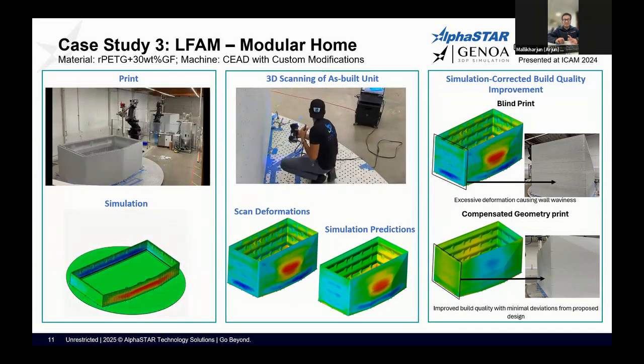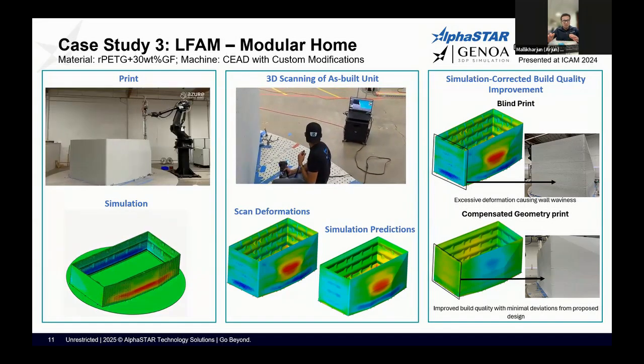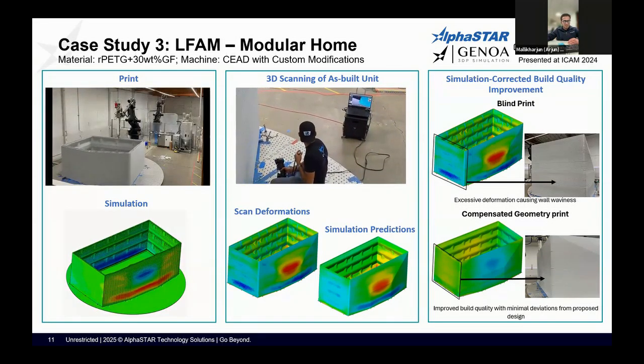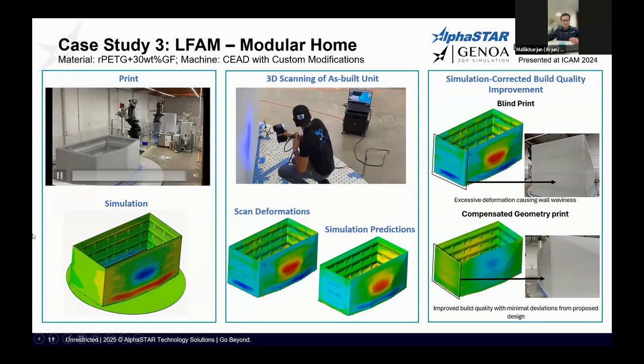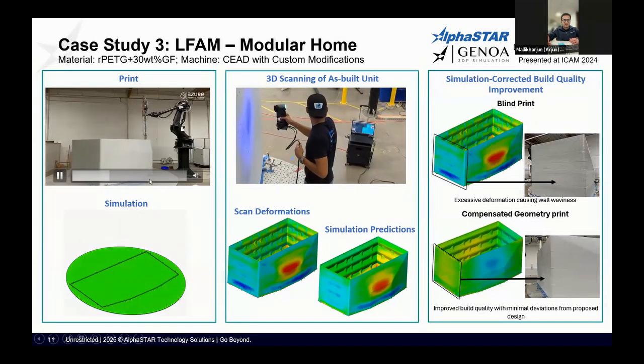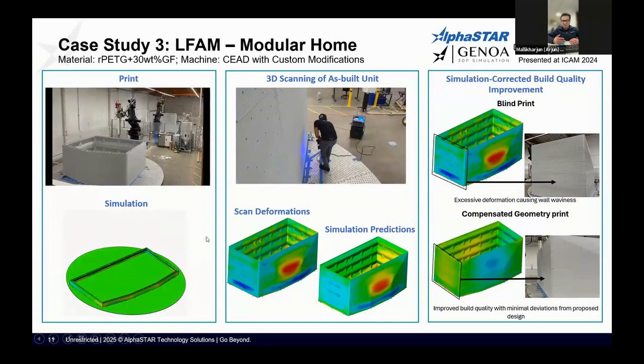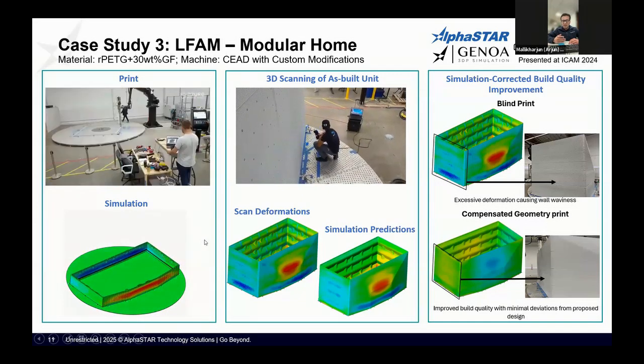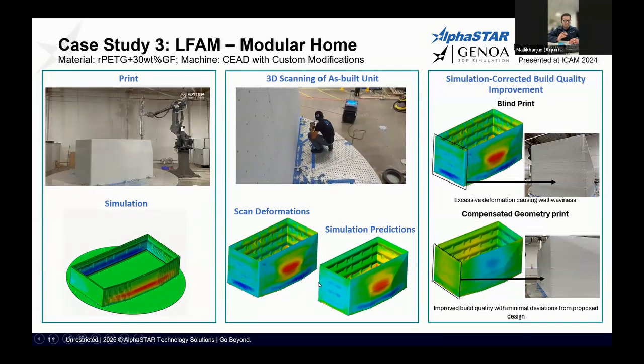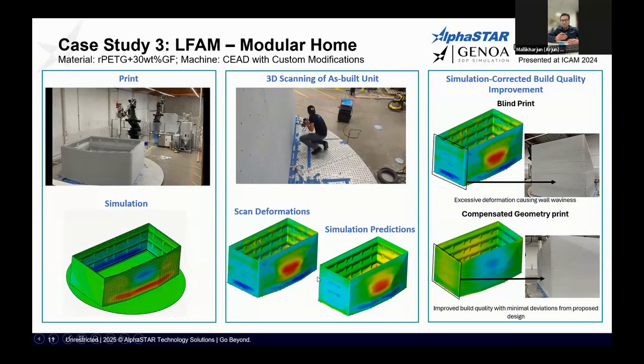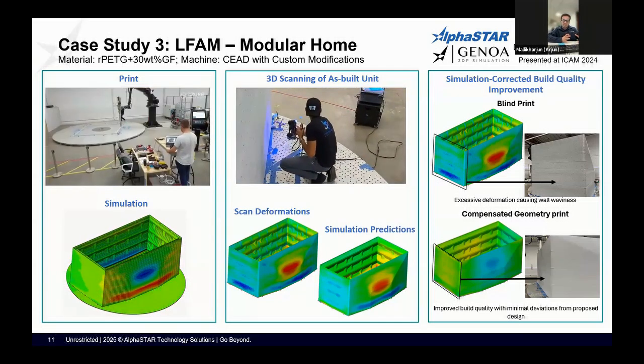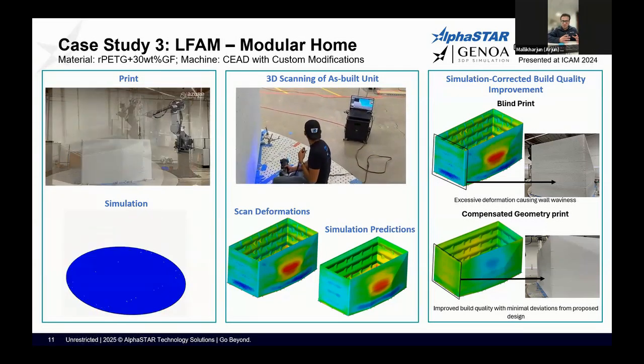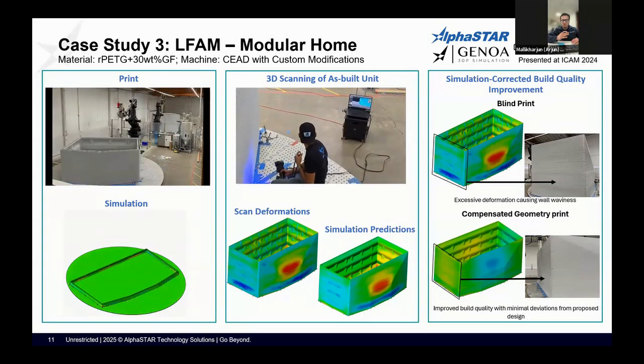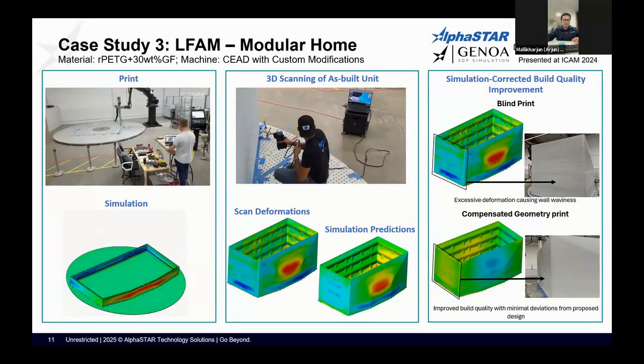When we say customizations, for this system, there is this build plate that's rotating, which is clamped down, then release the clamps. So there is a lot of details that need to be captured. So once we customize the solution, it's good to go. Now, in the same machine, same setup, if you plan to print a different geometry, we did all the hard work creating this customized solution, which means now you can go ahead and use that for other geometries on the same machine. That's what we did here.